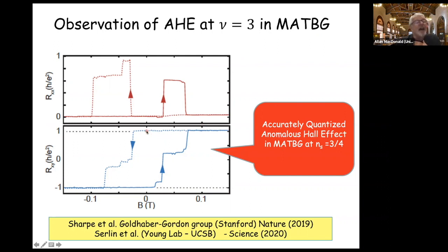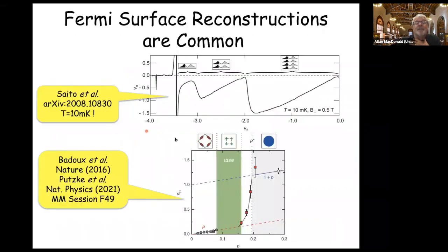But you see an experimentally pretty accurate, to a couple of percent, quantum anomalous Hall effect in the system, which is understood as a demonstration that, let's say, the conduction band has been emptied in this case for only one of four flavors, and that's the insulating state at filling factor -3. So that's one evidence that these spontaneous flavor polarization effects occur.